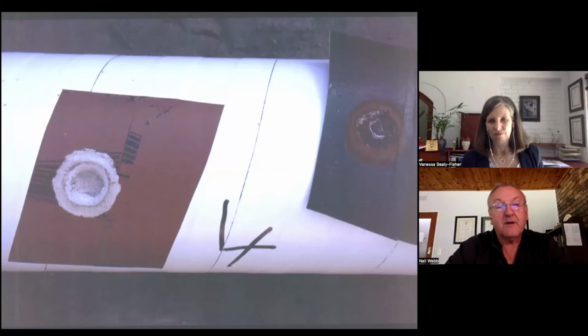This particular pipe did not have cathodic protection on it, and the pipe was perforated within 2 years. It was a fuel line. The net result was the line was scrapped before it was ever commissioned due to this challenge. Well, that immediately pushes up the price of the coating system.